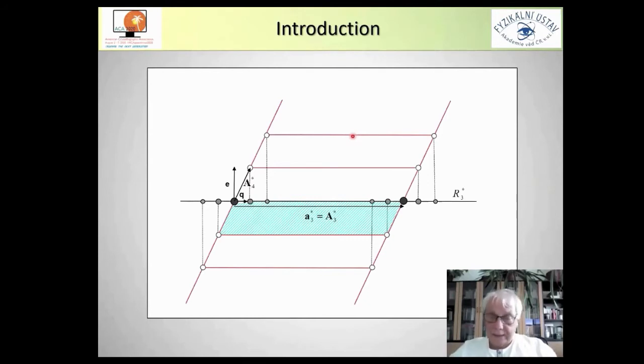But reality is different because this diffraction pattern has no lattice character, and from lattice character we have to return to real space, which means projecting back from this artificial space to the original one-dimensional crystal.